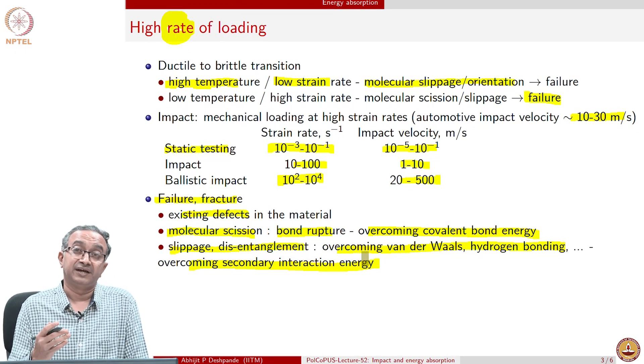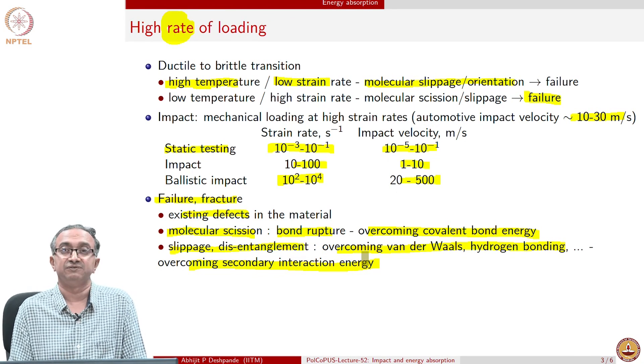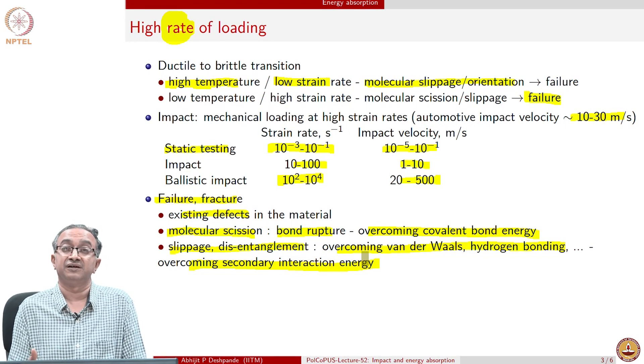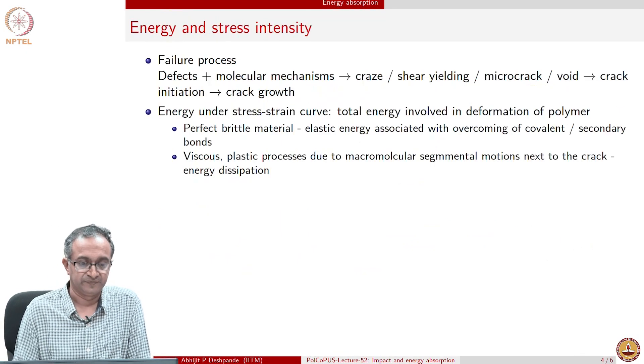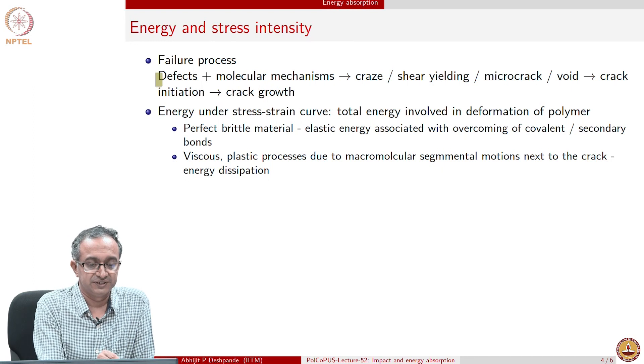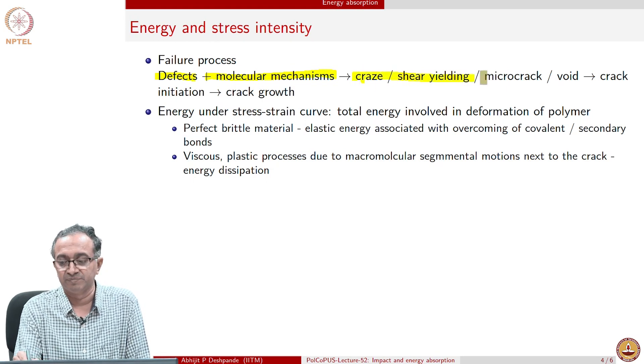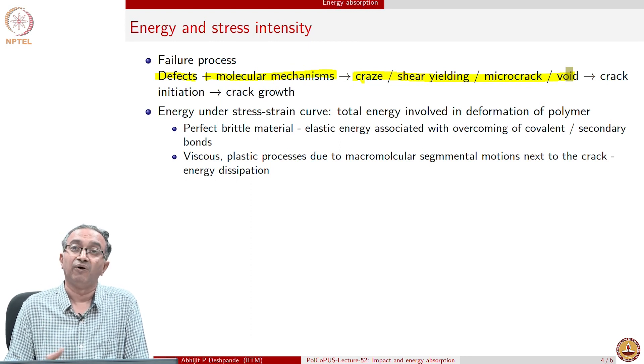This gives you an idea as to why rates matter. Depending on the rate, some of these processes will take place and some may not. Depending on the kinds of defects in the material and segmental flexibilities — whether slippage and disentanglement is possible — the overcoming of secondary interaction may or may not be possible at a given rate of loading. Therefore, different rates of loading lead to different kinds of mechanical response.